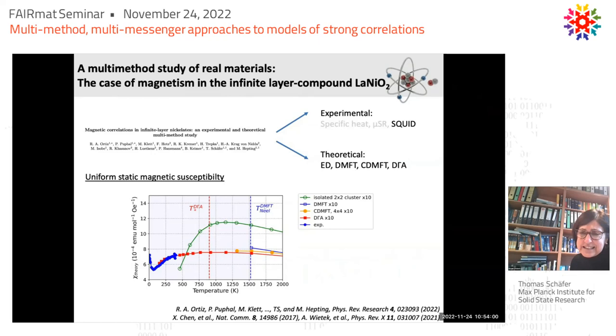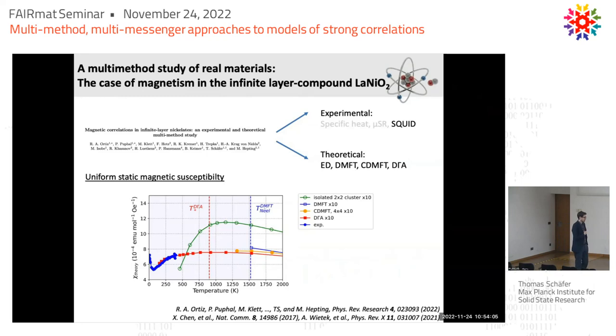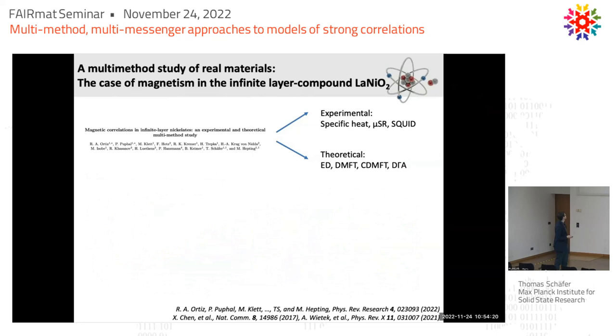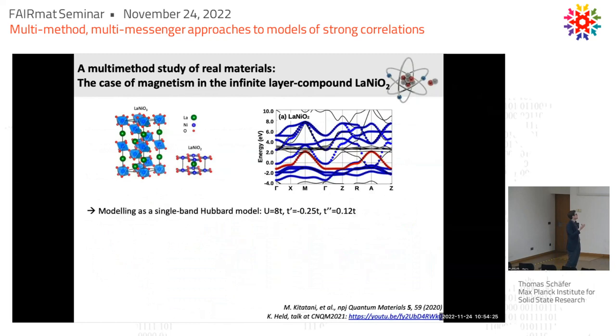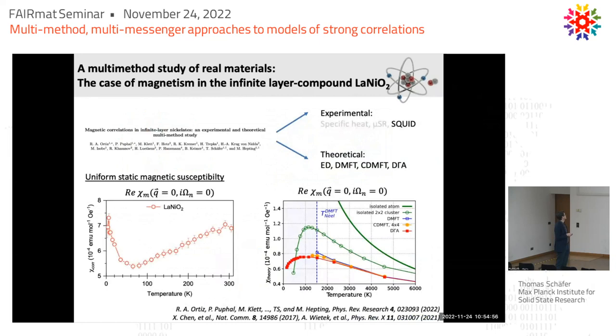I agree that the model is obviously rather general, and we also compared our curves to some cuprate experiments, and they agreed a bit better in the cuprates than in the nickelates. On the other hand, we also tried to adjust our parameters, because, for example, the interaction parameter stems from a CRPA calculation, and sometimes it's a bit of voodoo which exact parameter you should take. In this regime of the phase diagram, the actual value of the uniform susceptibility didn't change too much, so not the factor of 3. So this we can at least exclude in the approximation which DGA does. We trust DGA pretty much, because it has the same behavior as CDMFT, a completely different technique, and it can go to lower temperatures. So I think it's the best approximation we can do at the moment in this regime.